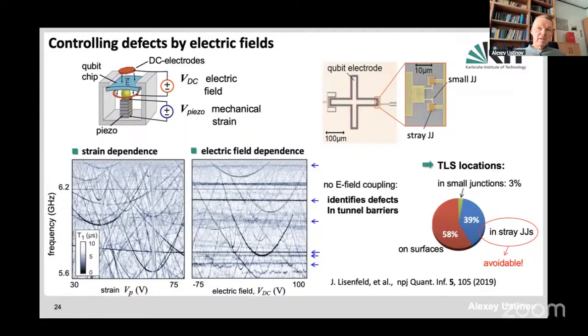However, this junction will also contain defects. And due to the large area, the electric field there will be, by the area ratio, lower than the electric field in the quantum junction. But nevertheless, the defects will be coupled to this field and can exchange energy with the quantum circuit. So in these first experiments, we found that the amount of defects in the stray junction was very high, about 40%, 39%. Of course, this all depends on the technology, on the foundry, on who makes the junction and so forth. So all these studies are not really covering the whole range of fabrication techniques around the world. But we have been working very closely with Google, for example, over the last several years to study the junctions fabricated at our place and also in other places.